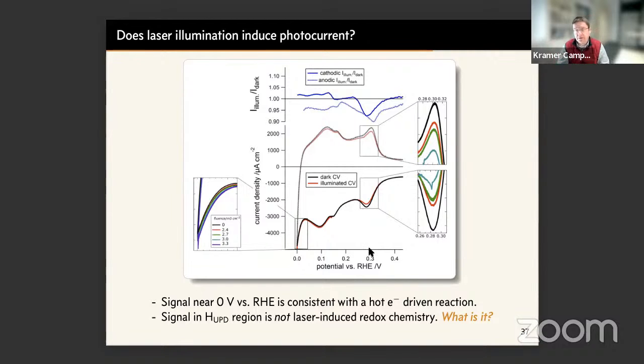And for those of you who've done these kinds of experiments before, the usual way this is interpreted is that one sees current features consistent with the different single crystals, right? A microelectrode is a combination of these different single crystal surface structures. The signal is obviously small, but if you zoom in on different regions, there's some very suggestive physics, right?